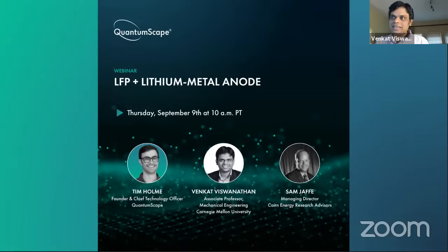What we find from the analysis is that you can certainly make an extremely cost competitive lithium LFP cell, which simultaneously addresses the market problem: you want low cost as well as high performance, so that you can have long range and high energy efficiency vehicles, as well as meeting the consumer price point of something in the $20,000 to $25,000 range. But all of this critically hinges on two factors. In the case of the anode-free configuration, it depends critically on the cost of the separator. And in the configuration with the lithium foil, the cost of the lithium foil predominantly determines how much cost savings you may have or not.